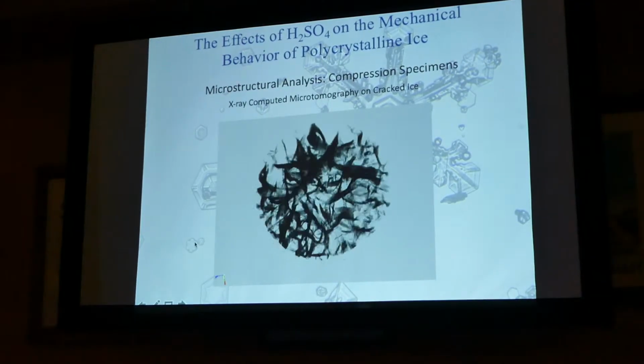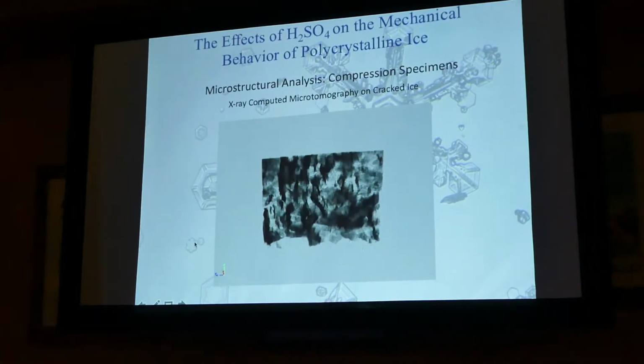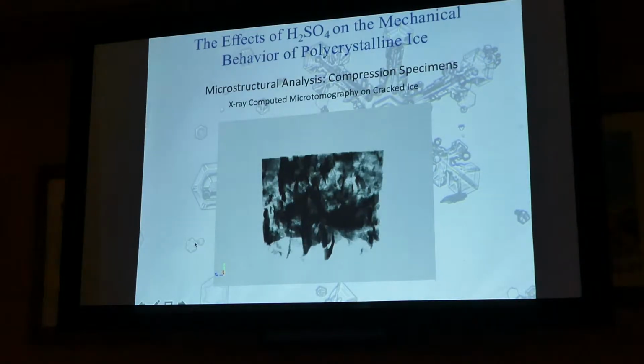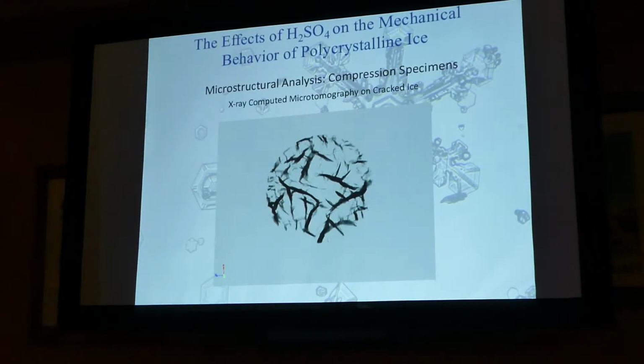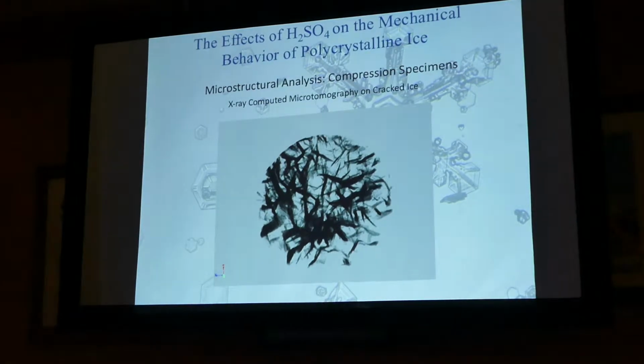So the black here are the cracks in the ice, and the clear is just the ice. So we're able to see these crack networks. We also were able to look at these under a microscope and see how the cracks kind of linked up and where they broke, which was always at the grain boundaries, right? Which is kind of what you'd expect. That's going to be the weakest point for these cracks to occur.